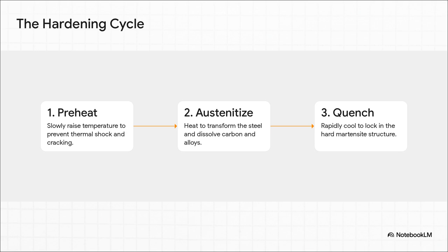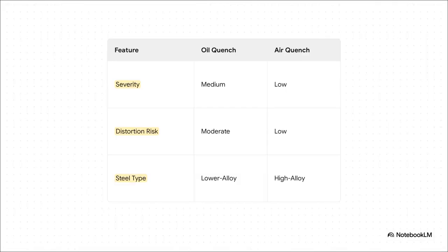This is that rapid cooling that locks in all that hardness, changing the steel from soft to incredibly hard. Now, quenching isn't a one-size-fits-all kind of deal. You have to choose your weapon carefully. For some simpler steels with fewer alloys, you need a really fast, pretty severe oil quench to get the job done. The downside, there's a decent risk the part could warp or distort.